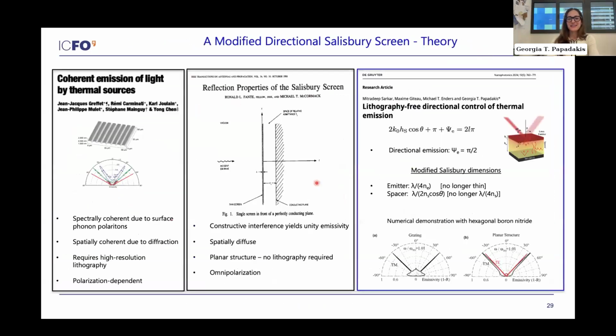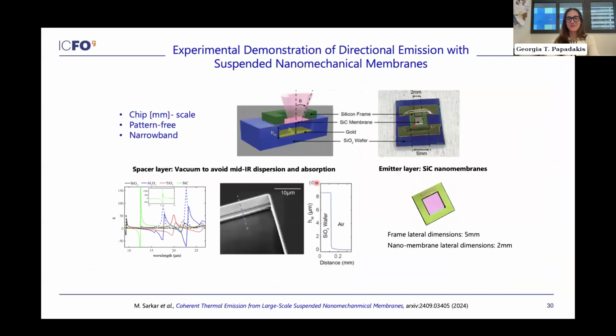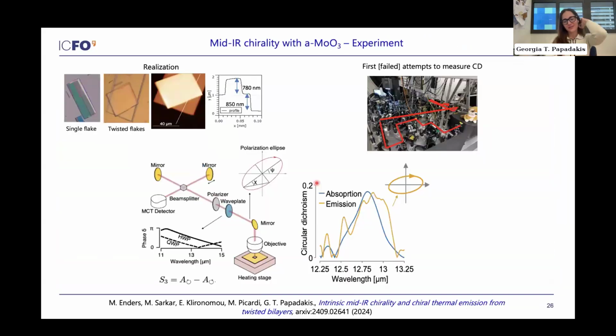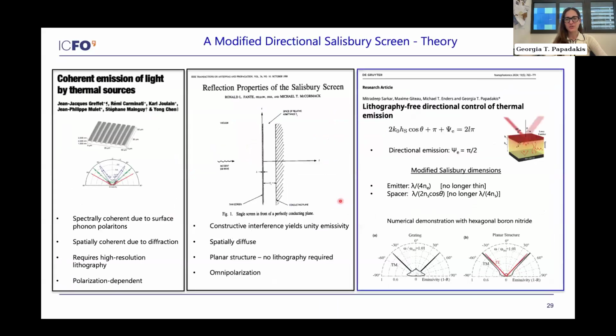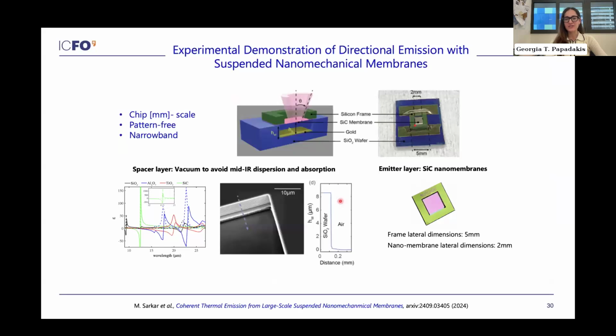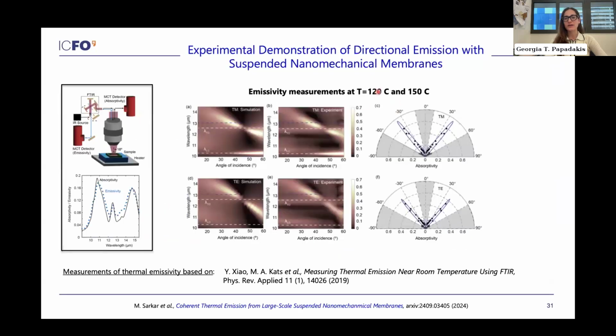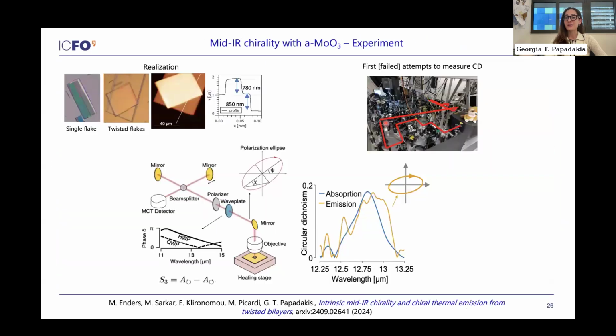Whoever this person is, he's probably done some painful measurements. Yes, the temperature, the real answer is I have to ask my student, but it's lower than 120 Celsius, because for silicon carbide we could go up to these temperatures, but molybdenum trioxide is very sensitive and it cannot tolerate these temperatures. So it's lower than 120 degrees.